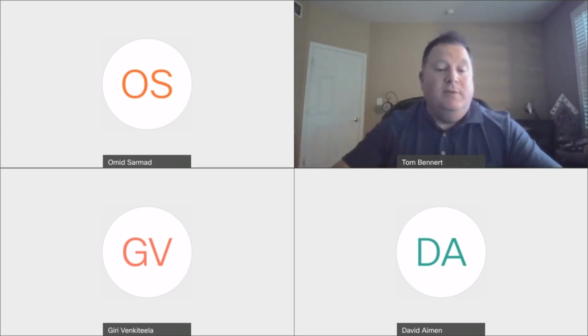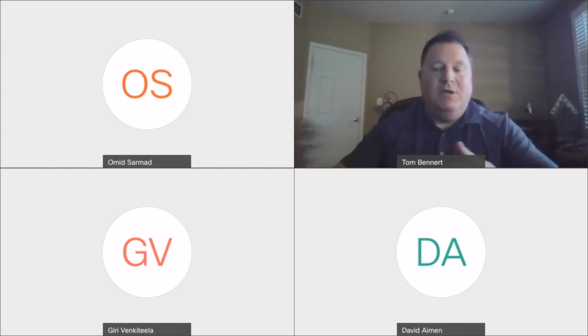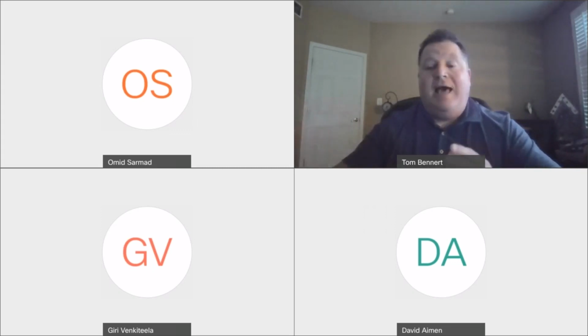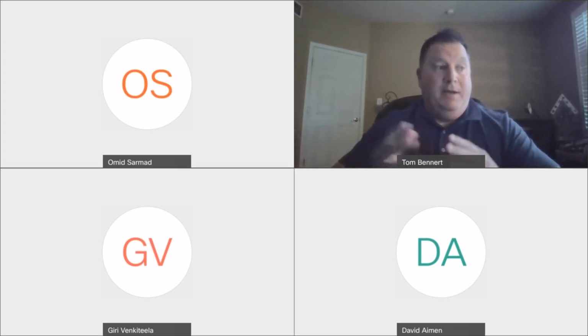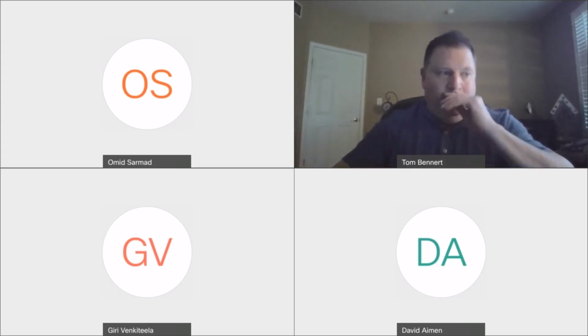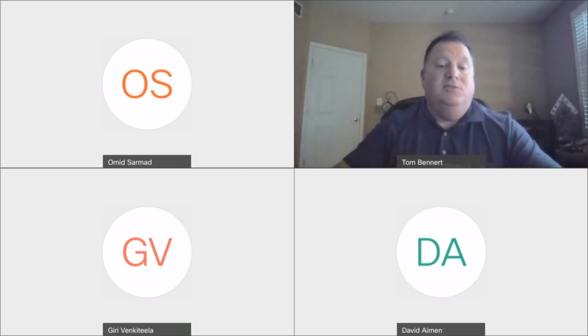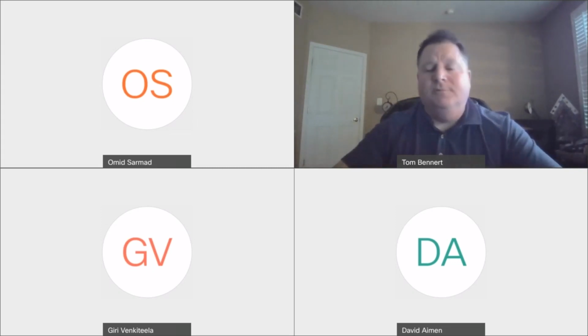There have been some instances where we've had some failures, which is what I showed in those pictures. And that was the idea of doing that work, to try to figure out what was the reason for the failures and what could we do to possibly stop that in the future, or at least reduce the potential for it. But it has been used successfully by the state as well as by municipalities. But again, there are some instances where it just isn't working because of the material it was put on. And that was the whole reason why we have the high friction chip seal as well, which is an alternate surface treatment that we're looking at to possibly be a substitute.